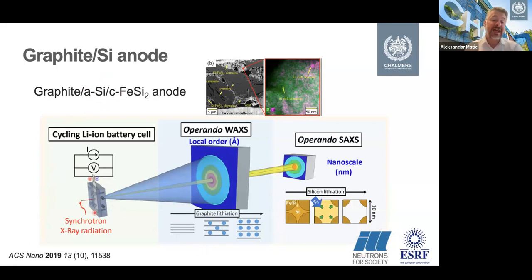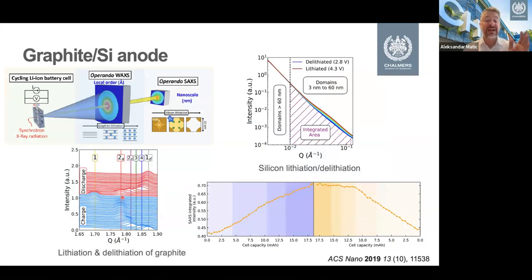They had a working cell, and then they recorded the diffraction pattern or wide angle X-ray scattering. And from this, they actually obtained the information on the local ordering in graphite. So they could follow when in the discharge and charge process we actually store in graphite. And then with small angle X-ray scattering, they could look at the nanoparticles or nanoparticle structures, which are a signature of the storage of lithium in silicon. So then they could follow and say, now we have an expansion of silicon and now we are storing more in graphite. So they could really differentiate between the two mechanisms.